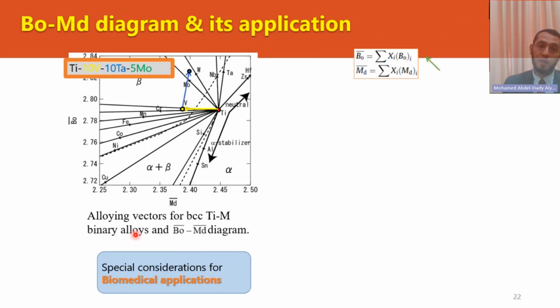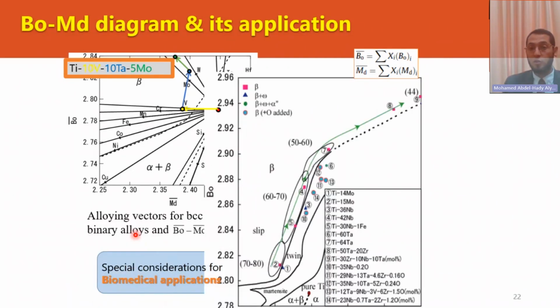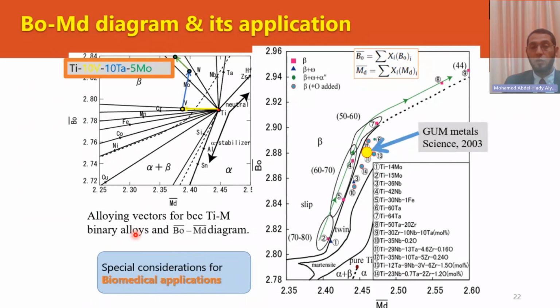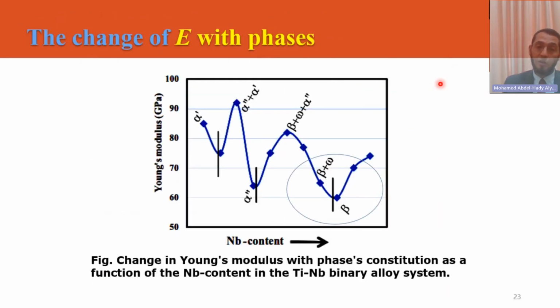So we do these calculations, and we can predict from the beginning how to design an alloy for biomedical use with specific phases, from the composition point of view, and also how to achieve low Young's modulus in this phase diagram. Low Young's modulus can be achieved in this diagram around this region. These values are the Young's modulus and so on. So as a function of the phases, Young's modulus changes with the beta stabilizing element content. You can see here different phases show different Young's modulus.